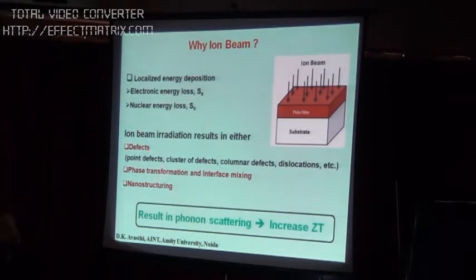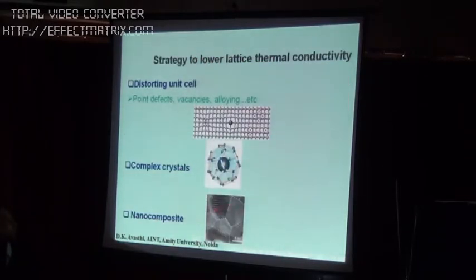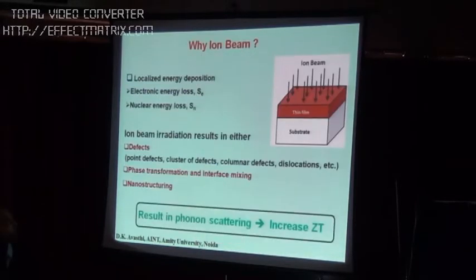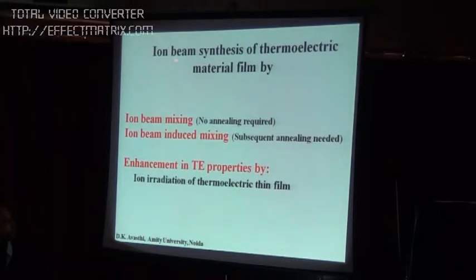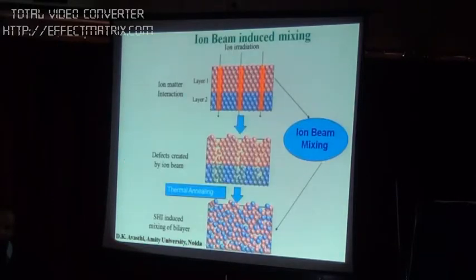So what we need is the creation of point defects and the creation of nanostructures, and I am getting both with ion beams. Defects I am able to get, and nanostructures I am able to get. That is how we want to lower the thermal conductivity and improve the efficiency. Now, ion beam synthesis of thermoelectric material thin films could be done by ion beam mixing or ion beam induced mixing. I'll explain the difference between the two. By ion irradiation one can also improve the thermoelectric thin film properties by inducing nanostructures.